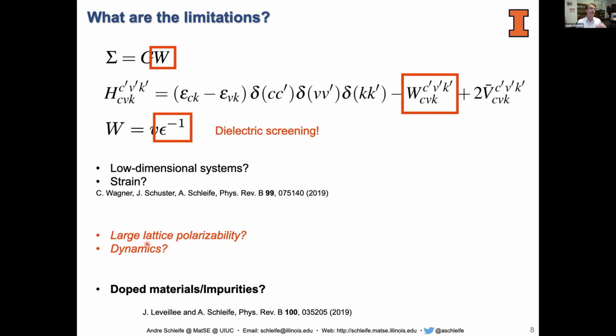So the fundamental approximation that many people make when they perform these simulations of the Bethe-Salpeter Hamiltonian is a so-called static approximation to the screening, which means that this screening term, which in reality is position and time dependent, or wave vector and frequency dependent if you Fourier transform, is approximated such that the dependence on the frequency goes away. And we believe we have indications that this is potentially a problem in materials with large lattice polarizability, simply because the lattice can also respond, but at a different time scale than the electrons. And so if you neglect that time dependence, you're losing that information. Anyway, I'll show you that in a moment.